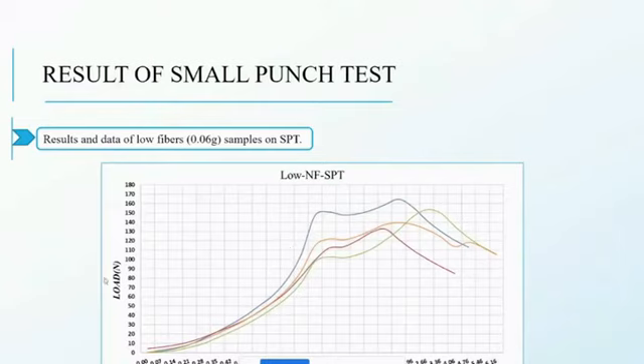Here we are showing the result for the low fiber. As we can see, this is the load displacement curve. It is following the very same trend for the small punch test. The good thing that we can notice here is that there is more resistance at the peak before the fracture. When the sample starts to fracture, it gives more resistance due to the introduced fiber, and then they start to fracture at the end. The average is around 140 newtons, which is logical for such a small sample.